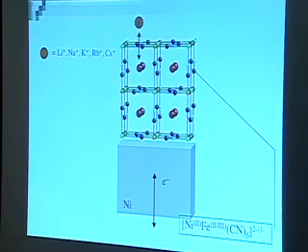change the charge on this lattice, and I have to keep electron neutrality. In the body-centered cubic position, these lattices will have whatever cations I used for my supporting electrolyte and have around. And so when I pump an electron in here, I will cause a cation to move in to counterbalance the charge. And when I pull an electron out through the electrode, I'll push a cation out into solution. And so I have an electrical current, if you will, a redox current on this side of the interface, and an ion current on that side of the interface, moving in and out. There goes my ion.